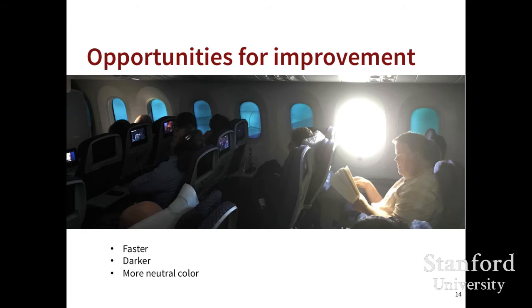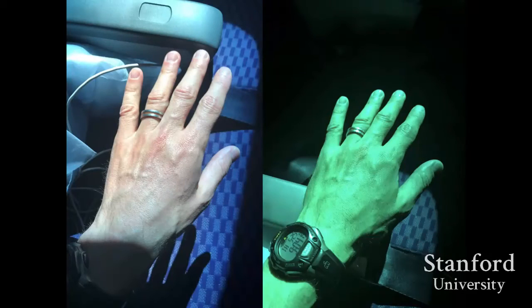But you also see that because the window switches over a period of minutes, a lot of people don't think it's working when they push the button, and so they keep pushing the button over and over. You also see that it's not currently dark enough for a lot of people if they're trying to sleep. And it's very bluish. In fact, in the next slide, you can see my hand when the window is in the clear state, and then my hand when it's in the dark state. And you can see that it's a very blue window.